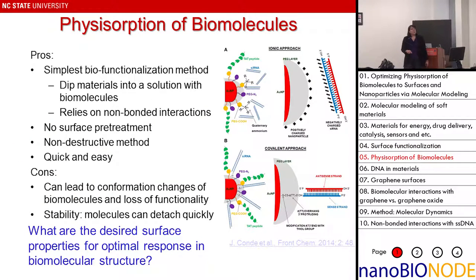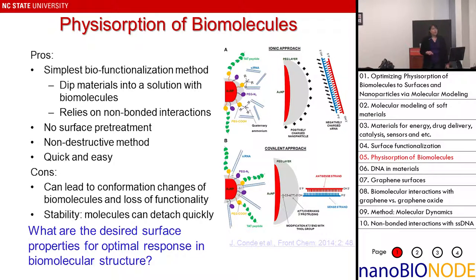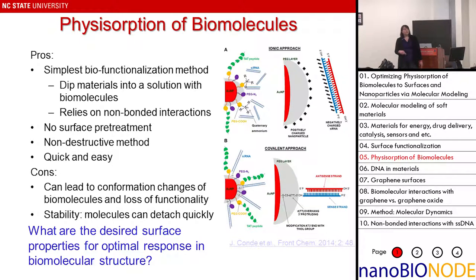We're specifically interested in physisorption. We use the covalent approach only to look at differences. Traditionally you can functionalize, say, siRNA to the surface through a linker — this is a permanent covalent attachment. Or with physisorption, you use a non-covalent approach where attachment of the biomolecule to the surface is driven by non-bonded interactions, which could be electrostatic, van der Waals, hydrogen bonds, or pi-pi stacking interactions.